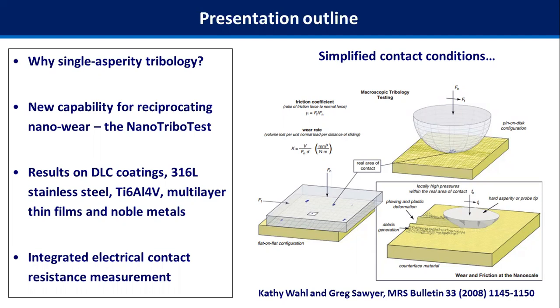So if we think about a conventional tribological test, the real area of contact is a small fraction of the apparent area of contact, and the contact zone is hidden, and this makes it difficult to really understand the pressures driving the failure events that we see. What we can do is simplify these contact conditions by moving to a single asperity contact and control these conditions and apply a known load, and therefore we've got a really good idea about the locally high pressures and what's driving the failure events that we see.